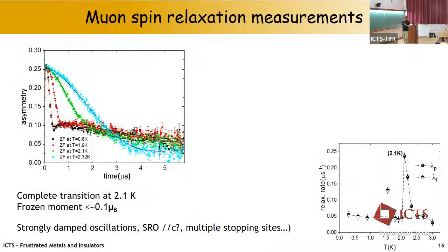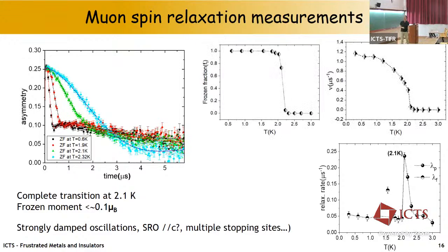So first, with μSR, we checked that the sample was fully ordering. So here you can see that there is a large change of asymmetry versus time when we go from 2.3K in blue to 1.9K in red, basically. So it's a very sharp transition. There is a peak in the relaxation rate at 2.1 Kelvin, so where we have a transition. This is the frozen fraction, which is going to 1. So the sample is one phase, one magnetic phase below 2.1 Kelvin.